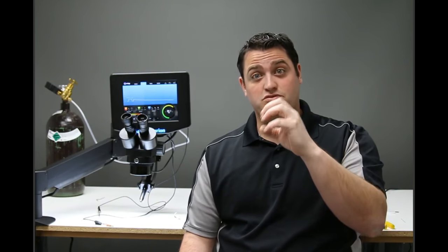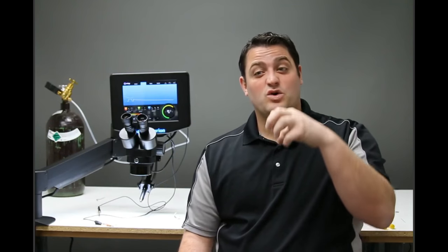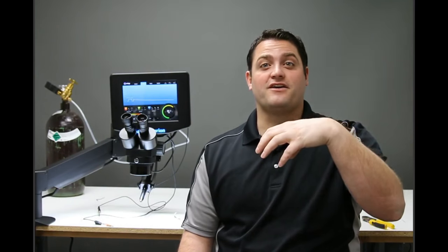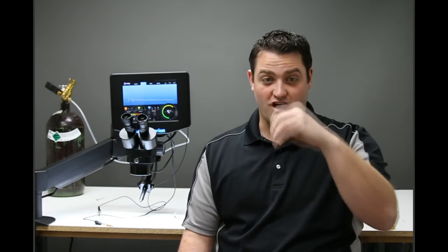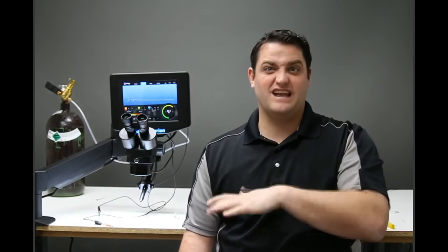One of the major problems that you have, because it's so mobile, is that the tip of the electrode tends to want to force energy straight down into the piece. What that does is, as the molten pool is forming, the energy is forcing it down, creating a concave crater or gouge, if you will. So as we weld, if we've got a really sharp electrode and our energy is turned up, so we've got a nice big melt spot, then as we hit that, it will tend to create a bigger crater than we originally had. Then you're chasing these craters around, and it's just pushing into the metal, making these divots where the energy is being pushed.